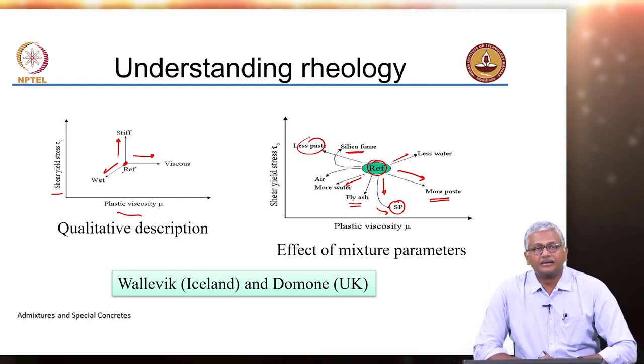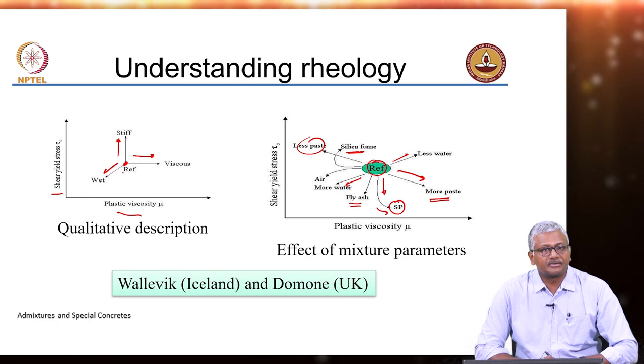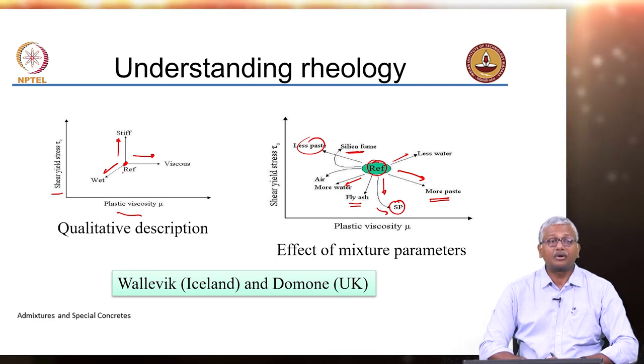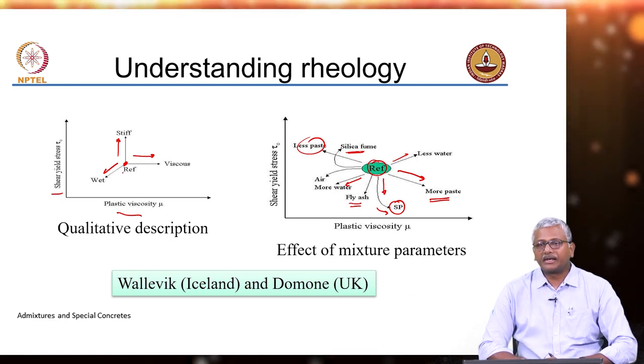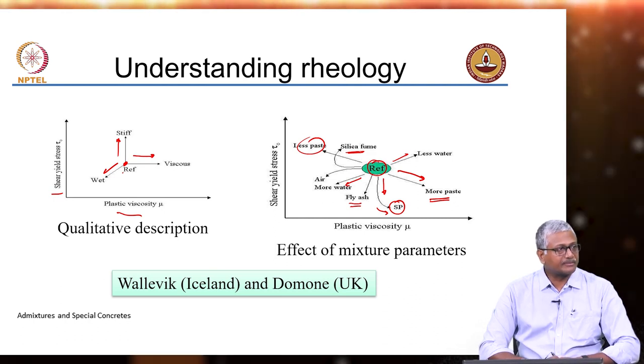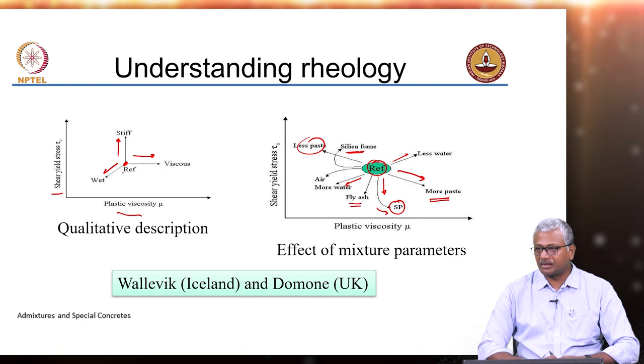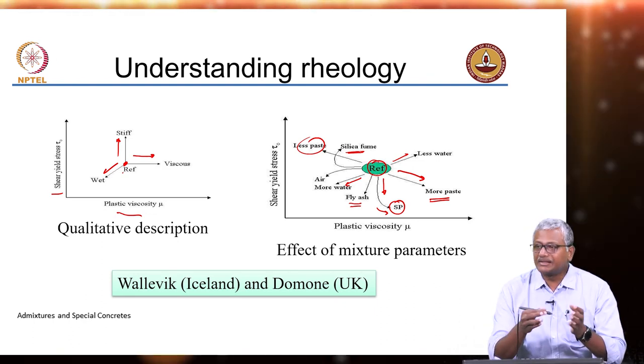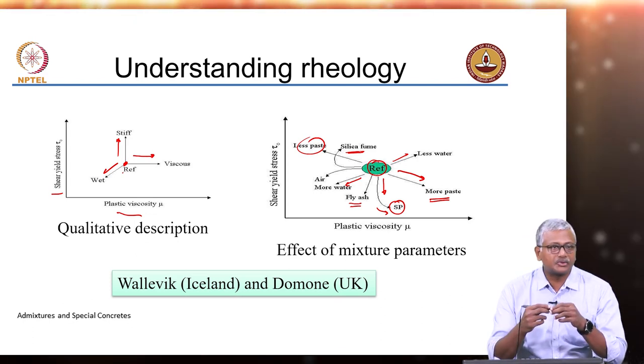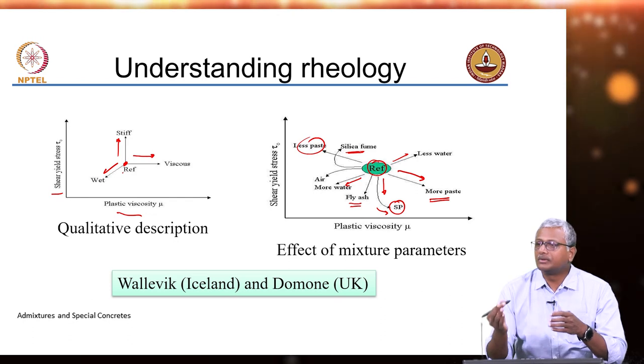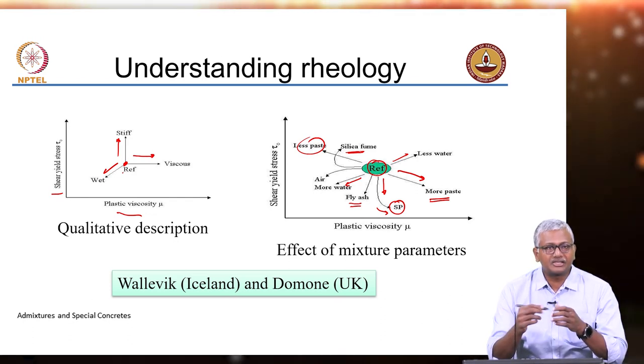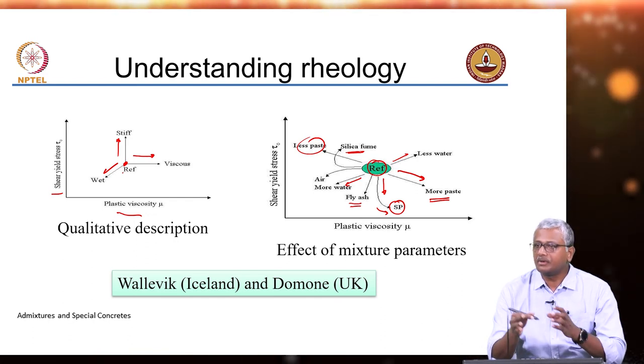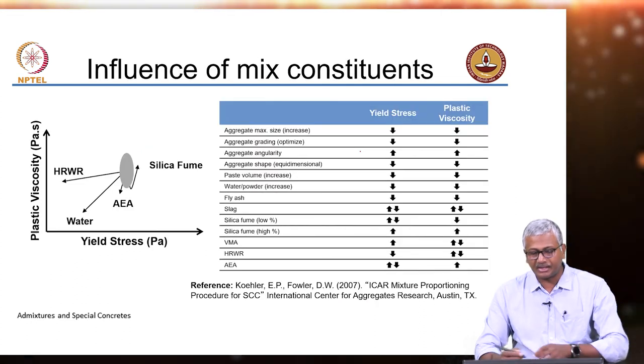Silica fume particles are very fine. If you replace cement with silica fume without altering water content or using a superplasticizer, you are likely to see a major enhancement in yield stress, meaning slump will go down significantly. The idea of looking at these two Bingham parameters — shear yield stress and plastic viscosity — can conveniently explain what happens to your concrete mixture as you alter the mix design and assess what constituents are required for specific applications.